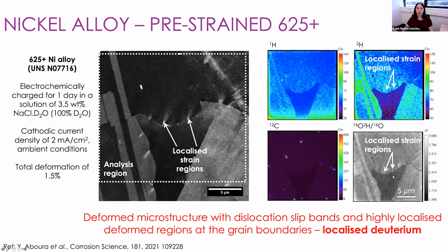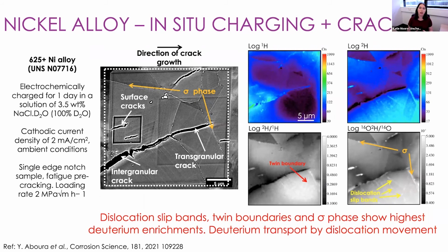Where we've got a deformed microstructure with dislocation slip bands and really highly localized deformed regions at the grain boundaries, we can now start to see localized deuterium. So we're seeing a relationship between dislocations and deuterium. Then we increase the complexity again. This time we were looking at in situ charging and cracking at the same time. This is a sample that's been fatigue pre-cracked with these conditions here, and all the conditions for charging are shown over here as well.